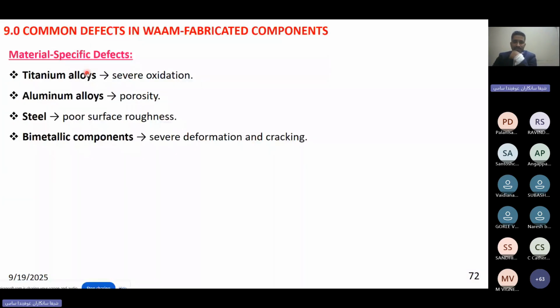And from some review articles I referred to, many people observed severe oxidation in titanium alloy, because titanium alloy is highly reactive. Therefore, if you are not properly using inert gases, oxygen pickup will be very high. For aluminum alloy, most people observed porosity because of the low melting element, and during formation, if the heat is very high, then porosity will be formed. For steel, they observed poor surface roughness, and severe deformation and cracking. These are the common defects usually observed by people.